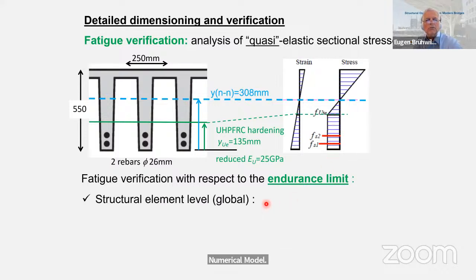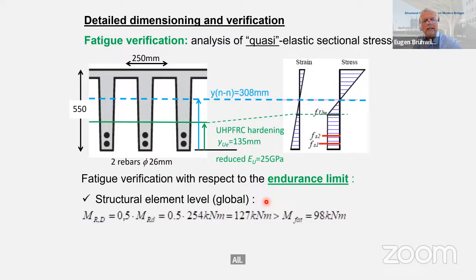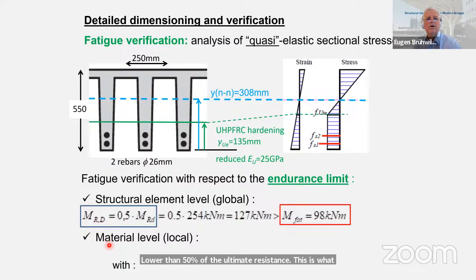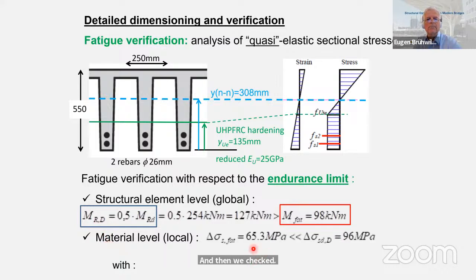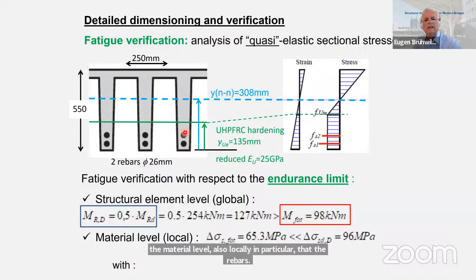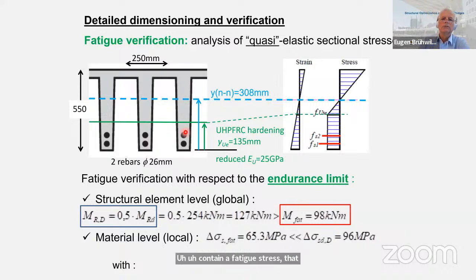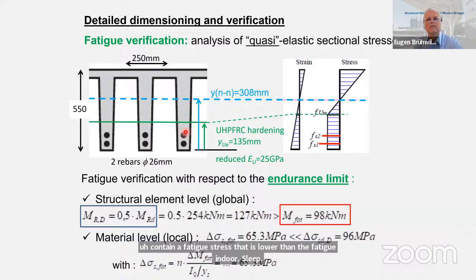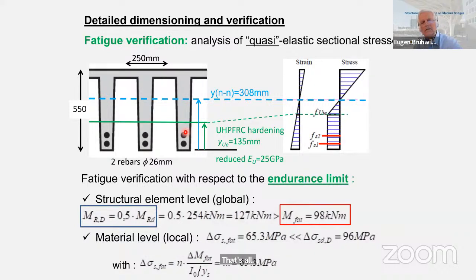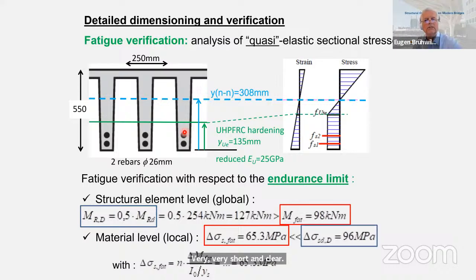So we verify on a global level, in terms of the structural element, which is a very simple verification. We need to keep the stress lower than 50% of the ultimate resistance. This is what this equation says. And then we check on the material level also locally, in particular that the rebars contain a fatigue stress that is lower than the fatigue endurance limit. That's all. Very, very short and clear fatigue design, but very important in this case.